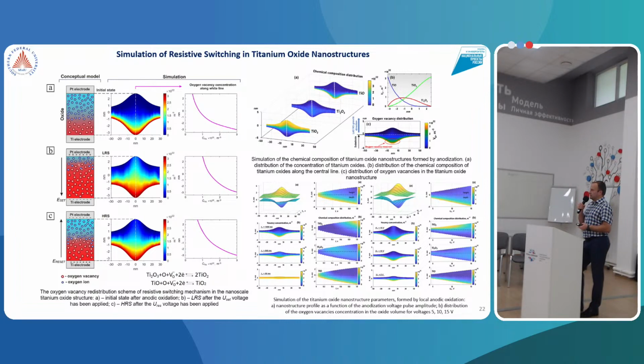We simulate this resistive switching in dynamics. On A, we present the situation after formation of the oxide nanostructure. On B, we switch the material to the low resistance state. We can see formation of a conductive nano bridge, and on C we present the breaking of this bridge and switching the titanium oxide nanostructure into the high resistive